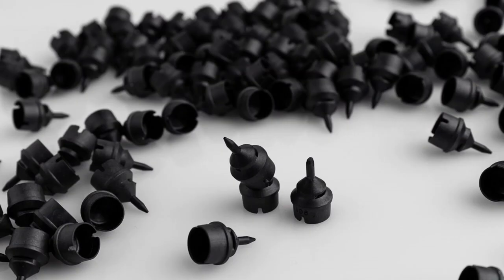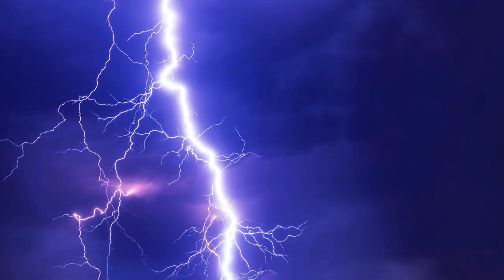There was a need for a wear-resistant material that also has electrostatic discharging properties for mounting components on PCBs with a pick-and-place nozzle, which you can see in the picture. Unfortunately for this application, the standard material provides only the wear resistance, but not electric conductivity. A zirconia-based material was created that has a resistivity between 10 and 100 megaohm. Now, both demands are served by a wear-resistant ESD-qualified ceramic.